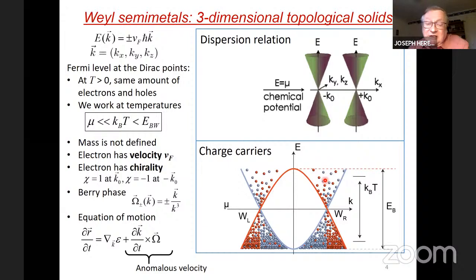And once we get to temperatures so that carriers can be excited from one valley to the other, then of course the phenomena disappear. But most of the time we will work in a kT region where we have thermally excited electrons and holes of the same amount, or nearly the same amount. Because of this linear dispersion, we do not have the concept of effective mass or really the concept of mobility. Electrons have a chirality, they have a Berry phase, and because of their Berry phase in the equations of motion, they develop an anomalous velocity, which would show up in the transport properties. We hope to prove that.